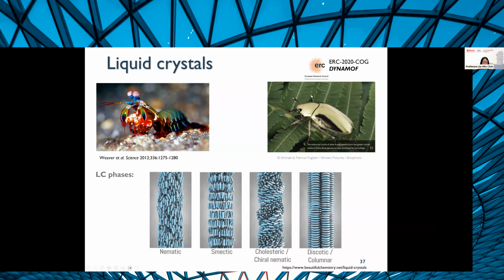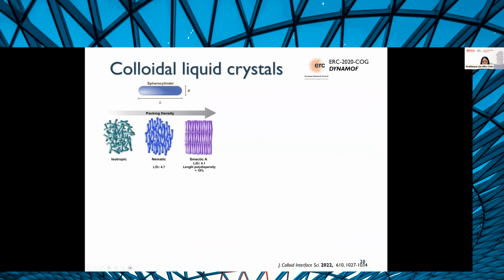polarized light. But besides molecules or polymers that can form liquid crystalline phases, particles can also do this. Particles can form these nematic phases, whereby they have a directional preference. They can form smectic phases, where you not just have direction, but also the formation of layers. And if you have chiral interactions, they can form cholesteric crystals, like in the case of these mantis shrimp, or they can form discotic liquid crystals as well. So we thought, there are examples of particles forming these. Why not MOF materials? And MOFs are especially exciting because you can really tune these particles for liquid crystal assembly.